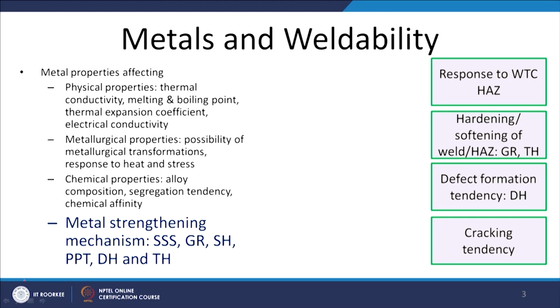As far as the response to the weld thermal cycle is concerned, when we are developing the weld joint through a fusion based approach, a narrow heat affected zone is developed due to the weld thermal cycle being applied, but the influence of the weld thermal cycle on the properties of the heat affected zone as well as on the properties of the weld metal will depend significantly on the underlying strengthening mechanism of the material.